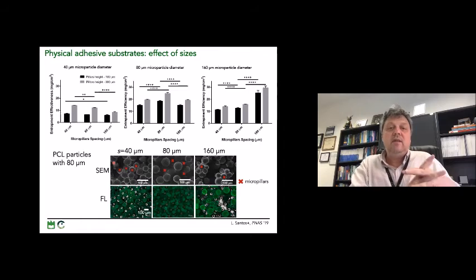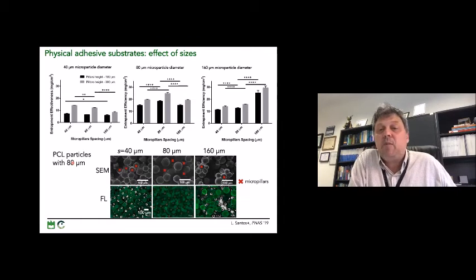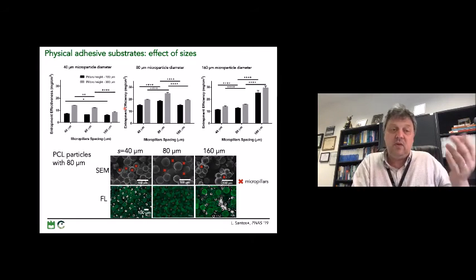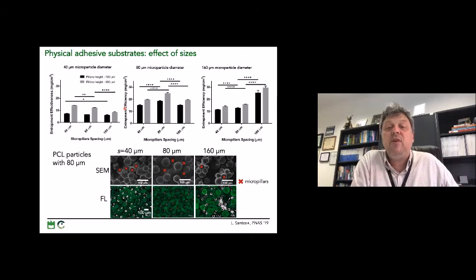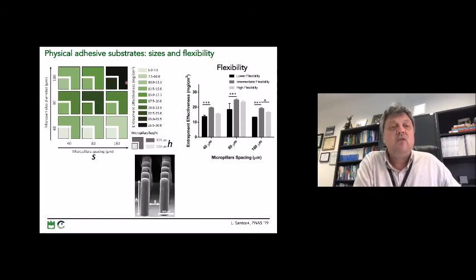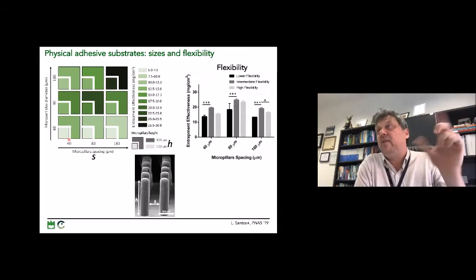Of course, I'm not going into details, but we prepared particles of polycaprolactone with very controlled sizes of 40, 80, and 160 micrometers. And we fixed them into the membranes with pillars with a similar distance for the 3 sizes. And we measured the entrapment efficiency in order to check if the hypothesis was really valid. So to go faster, I will go for a color map. I think it's much easier to see. You can visualize here the entrapment efficiency, which increases with the increasing green darkness, as a function of the micropillar spacing, S, and the microparticle diameter. You can see that you have more entrapment efficiency in this diagonal. The diagonal corresponds to the matching between the 2 sizes, okay?